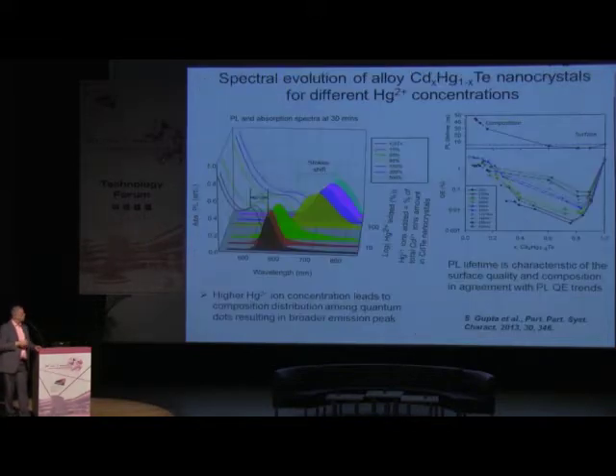We typically look at the fate of those particles using optical absorption and photoluminescence spectroscopy as the major tools. For example, what we can see from this slide is that the higher mercury ion concentration which we introduce indeed moves emission of those alloy nanocrystals towards longer wavelengths, and this is nice because by that we go into the near infrared region. Also this characteristic Stokes shift, the difference between absorption where we can excite them and the PL maximum, changes, and this all gives us some hints how distribution of mercury occurs when we conduct such kind of reactions.